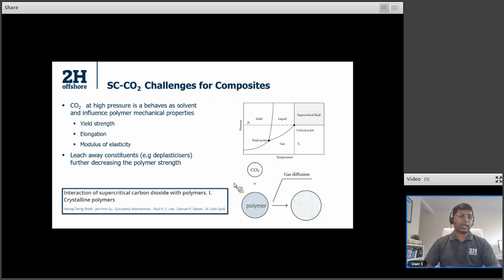Further, some of the CO2 could also be embedded within the polymer structure itself, but due to the nature of its movement back and forth, it could leach away some of the additional constituents that we add for plasticizing the polymer, which means it could result in failure modes by thinning of your polymer and losing strength of your polymer. So this is something that the industry still needs to look into if we are using composite pipes to venture into an environment which faces supercritical CO2.